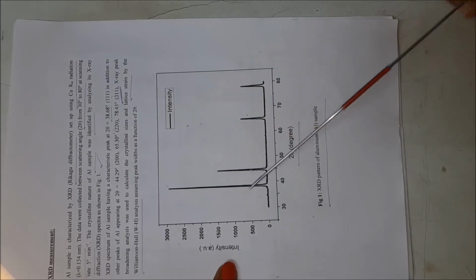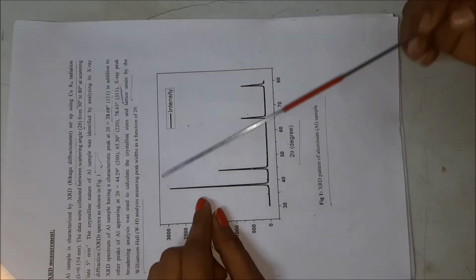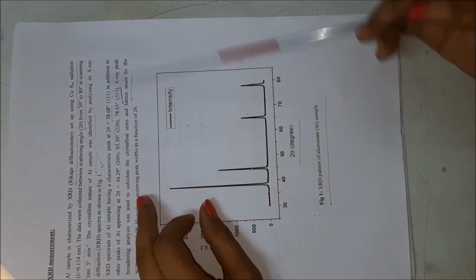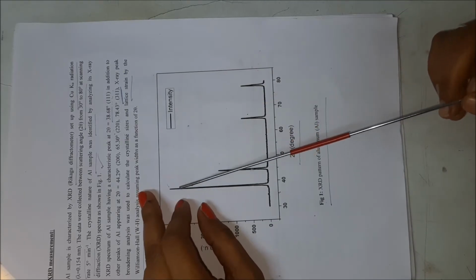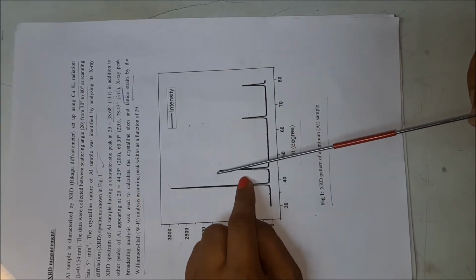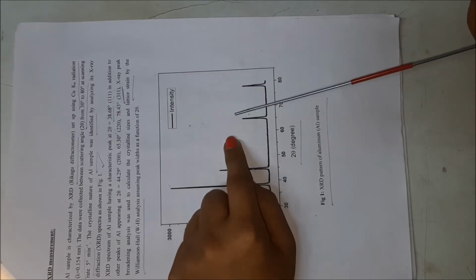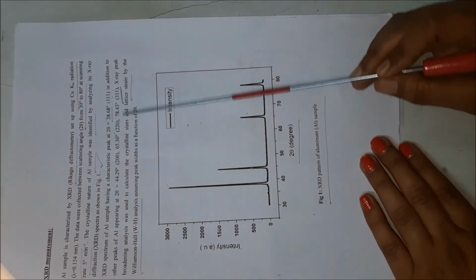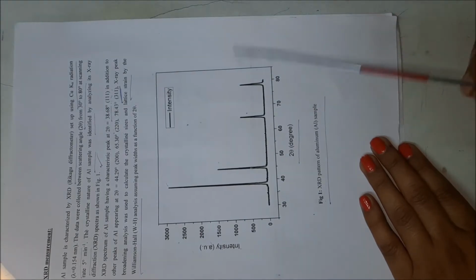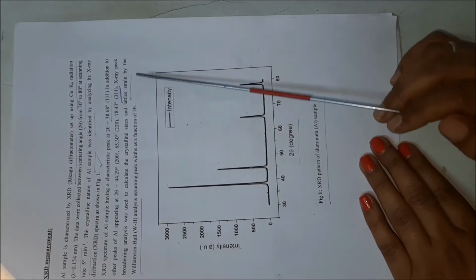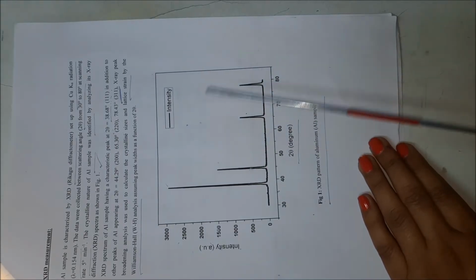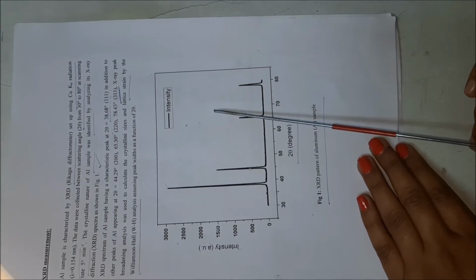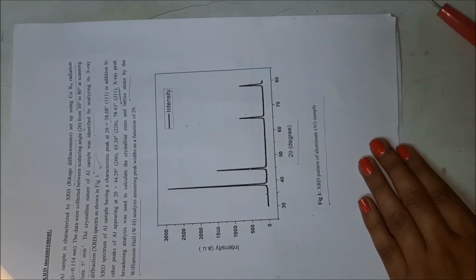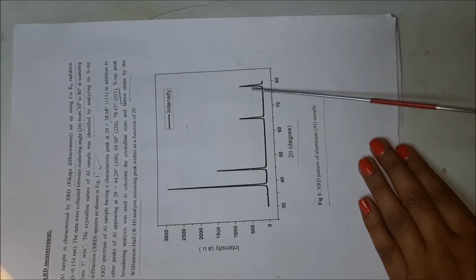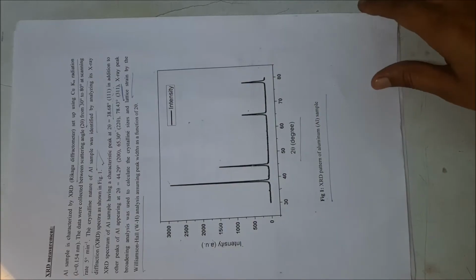Here, many peaks arise corresponding to different angles: the first one is 38.68 degrees, the second one is 44.29 degrees, the third one is 65.3 degrees, and the fourth is 78.4 degrees. And with the help of this XRD pattern, we can calculate the crystallite size with the help of the Scherrer formula. But by using the WH equation, we can calculate the crystallite size as well as the lattice strain of the sample.